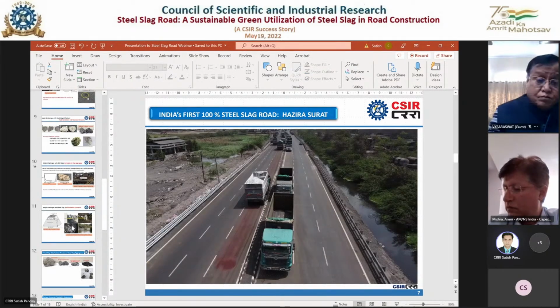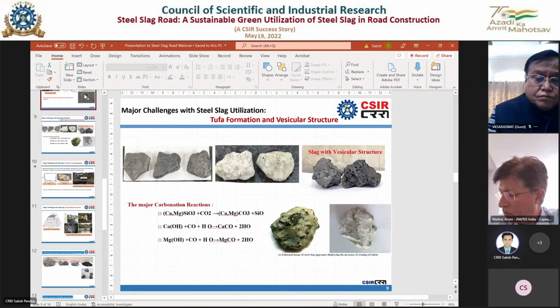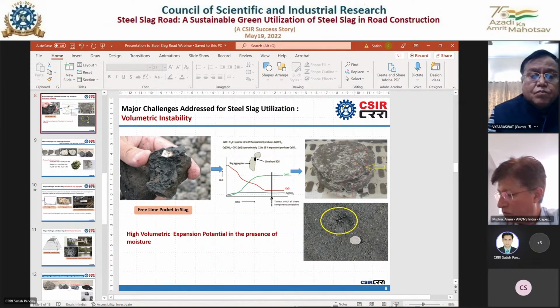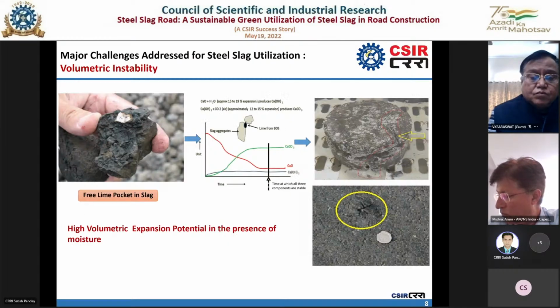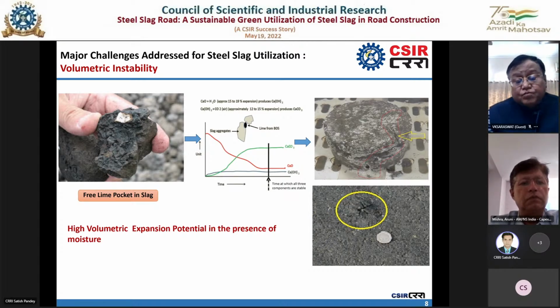And the different types of challenges we have addressed for steel slag utilization in this journey are, first, the volumetric instability, as the sir has discussed. Steel slag shows volumetric instability due to the presence of free lime and magnesia. So we modified the steel slag cooling process so that stable mineralogical phases can be formed, and besides that, the requirement of weathering can be further reduced. So this sort of distress cannot occur in the pavement when processed steel slag is utilized for construction.